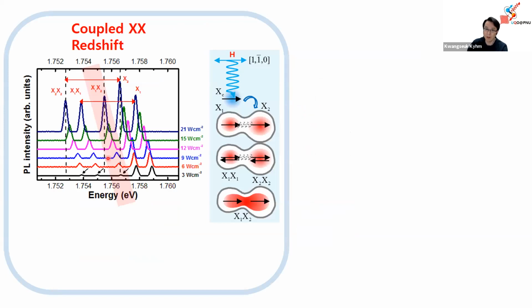Initially we studied microphotoluminescence for increasing excitation power. As you see, under non-resonant excitation with H polarization, after interrelaxation carriers are injected, but the dipole is still affected by the initial linear polarization. We think there might be some carrier distribution around the interface that induces a kind of local field, and the local field induces such alignment. This is the X1 exciton from the small quantum dot, therefore the energy level is a bit high, and X2 from the larger quantum dot, low energy. You can also find local biexcitons corresponding to the excitons, for example X2X2 and X1X1 from here. The binding energy is roughly 5 millielectron volts, nearly the same for both.